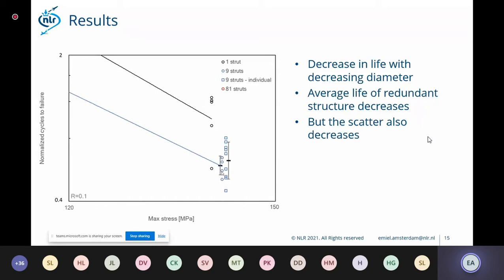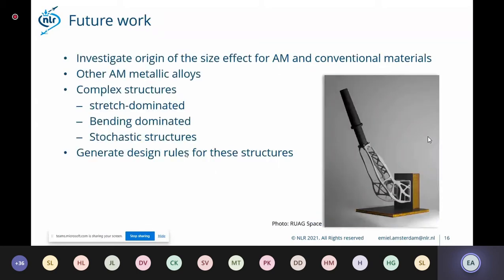So this is already a good result, but we still have the difference in life between the different diameters. That's something we have to investigate further. This is done in a project starting in September by another student, and he will investigate the origin of the size effects for additive manufactured materials and conventional materials. We use other alloys and more complex structures, so that in the end we have design rules which would guarantee such a structure as this antenna, that it's damage tolerant. So if, for example, this very small strut is missing, it does not lead to direct failure of the entire structure.